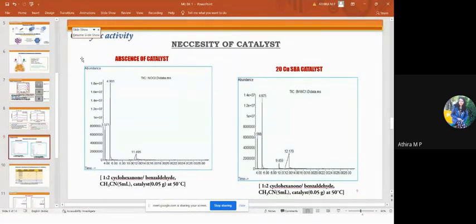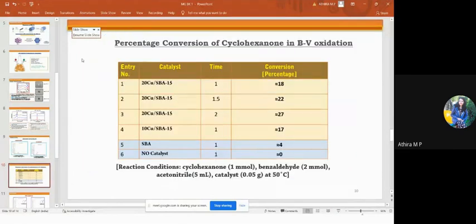And we have checked the necessity of the catalyst in this liquid phase oxidation reaction. In the absence of catalyst, we didn't find any peak regarding caprolactone. In the presence of catalyst, we obtained a peak of caprolactone at a retention time of 9.4545. And this is the percentage conversion of cyclohexanone in the Baeyer-Villiger oxidation reaction.